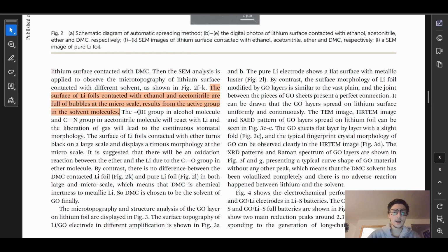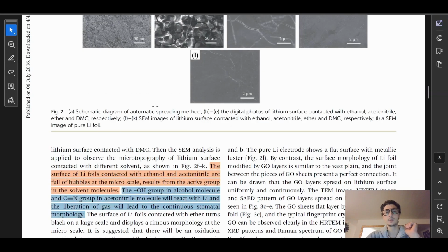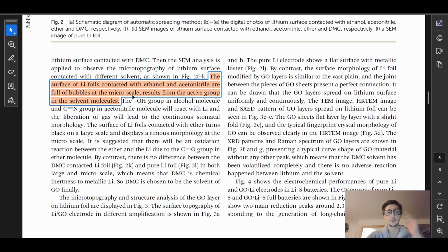The -OH, I think this is the hydroxide group. I'm not sure. Gotta brush up on the chemistry here. The hydroxide group in alcohol molecule and the C triple bond N group in the acetonitrile molecule will react with lithium, and liberation of gas will lead to the continuous stomatal morphology. Interesting. So they actually give an explanation of why these two things happen here, because the solvents they use have groups that mess up with the lithium.